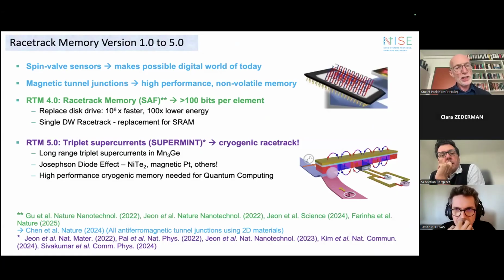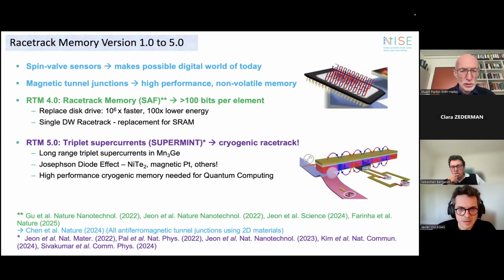Same time, racetrack memory, which I've worked on for many years, but nevertheless, we now believe we have demonstrated it does work in racetracks just 50 nanometers wide, and therefore, technologically, the length scale is such that would enable us to build a racetrack device that would have the same capacity as a disk drive, but be 1,000,000 times faster to access the first bit and 100 times lower energy. And I didn't mention this, but a single domain wall racetrack, we can move the domain wall backwards and forwards very fast at speeds of a few picoseconds. So this could be a replacement for the fastest conventional volatile memory today, which is static random access memory. But a single domain wall racetrack would be non-volatile.